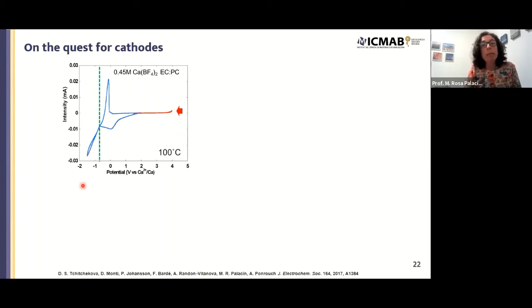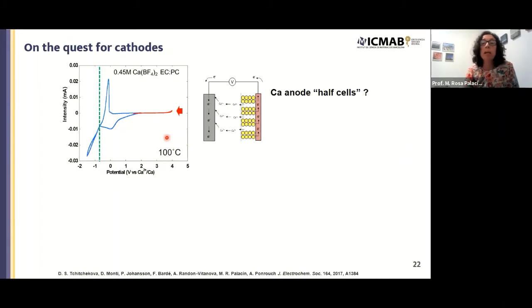Once we had the electrolyte which was enabling calcium plating and stripping, we wanted to look for cathodes to prove the concept. In fact, one of the advantages of this electrolyte is that it is compatible with high voltage cathodes, even at 100 degrees C. The first thing is the development of the protocols, and we had a lot of issues with that.